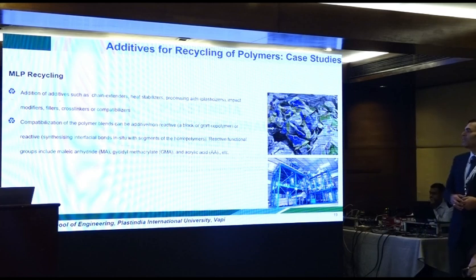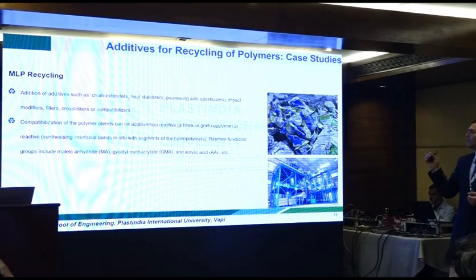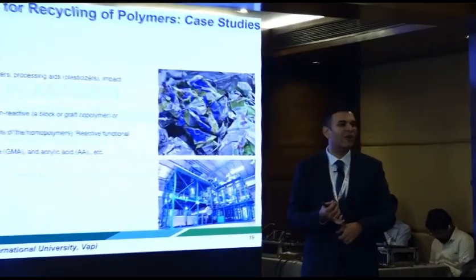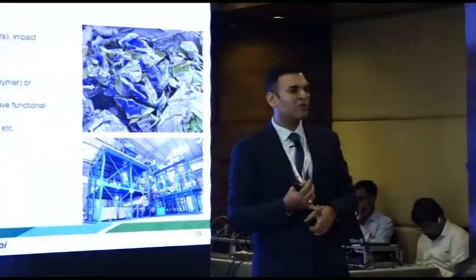Compatibilization of the polymer blends can be done by an additive or a non-reactive, that is you can use a block or a graft copolymer, again will have multiple functionalities present in it, or reactive. So reactive functional groups include maleic anhydride, GMA and acrylic acid. So maleic anhydride, we all know it's quite popular for PP. So PP that we use in filled compositions, it is seldom PP ever, it is always maleiated PP.